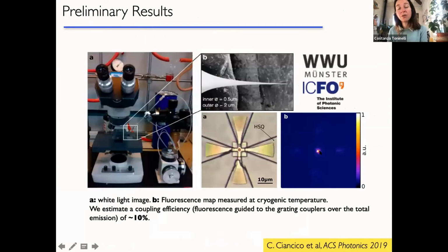And we have really started using them to integrate them in photonic structures of different kinds. One project we had was in collaboration with ICFO, in which we deposited by a microinfiltration setup our nanocrystal in a small hole, and then we used electron beam lithography to cover this hole and not have nanocrystals all over the place. And already you see that there was some fluorescence, this is the nanocrystal doped with many molecules.